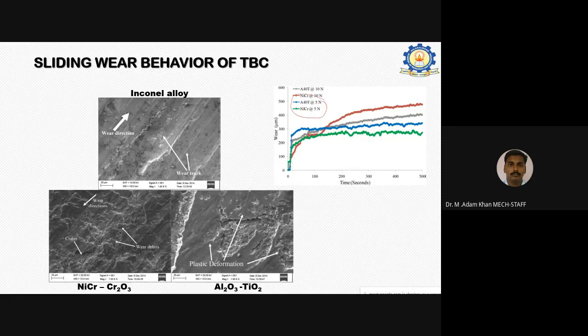This is for nickel chromium. And for alumina, it is around 300 microns. When the load goes up to the maximum, it has crossed around 500 microns for 30 minutes at this much load. So we will be designing for maximum load. 10 Newton, 5 Newton is a maximum load, so that it is able to bear the working load in the working environment.